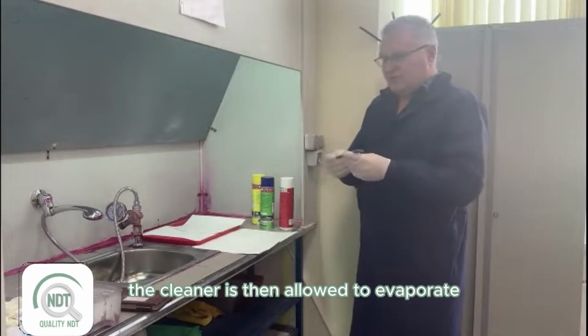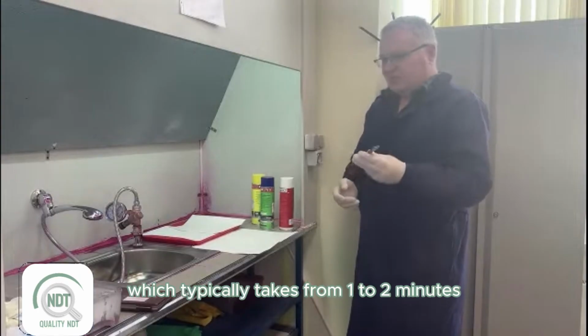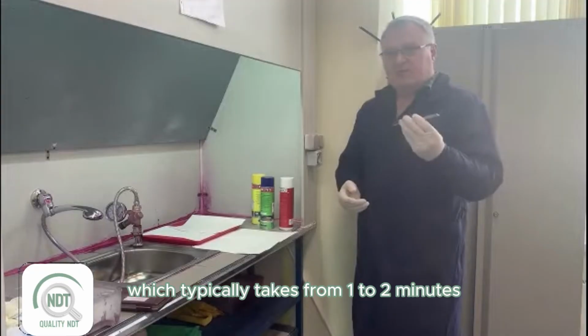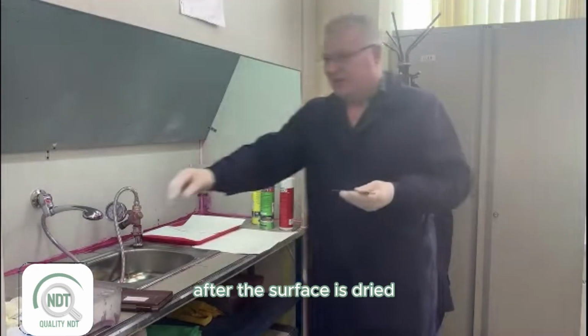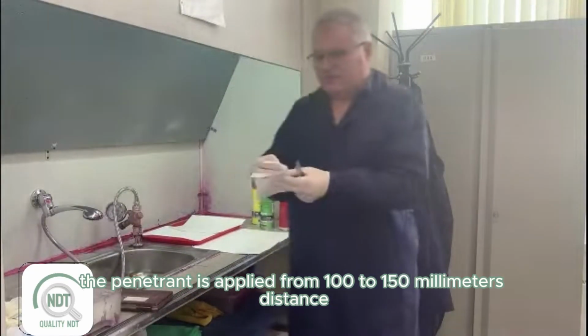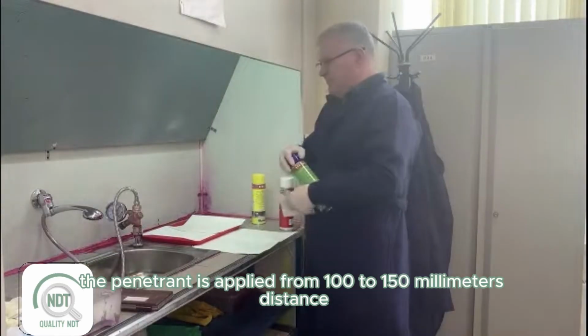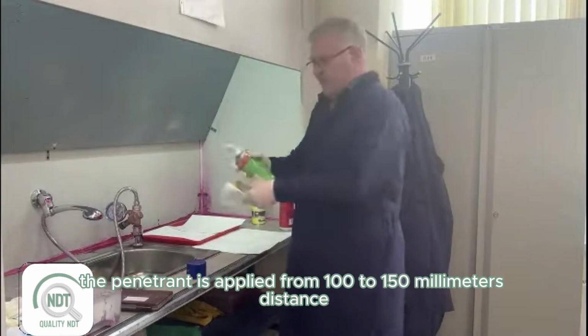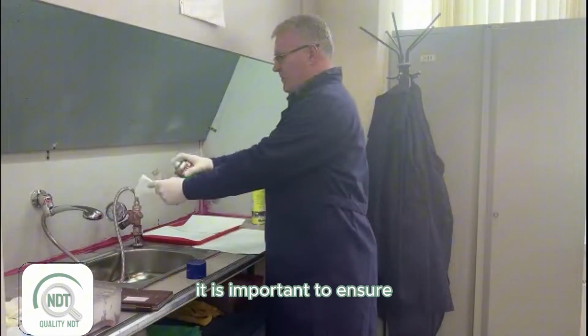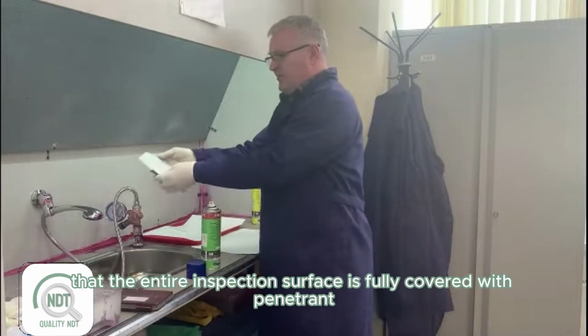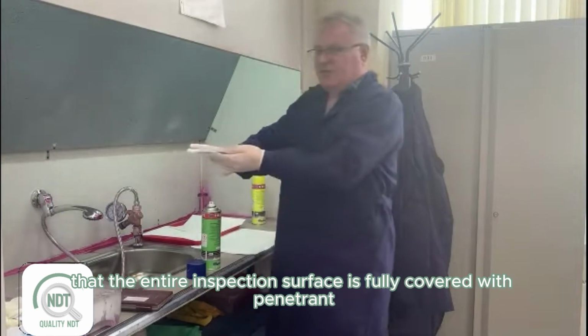The cleaner is then allowed to evaporate, which typically takes from 1 to 2 minutes. After the surface is dried, the penetrant is applied from a distance of 100 to 150 mm. It is important to ensure that the entire inspection surface is fully covered with penetrant.